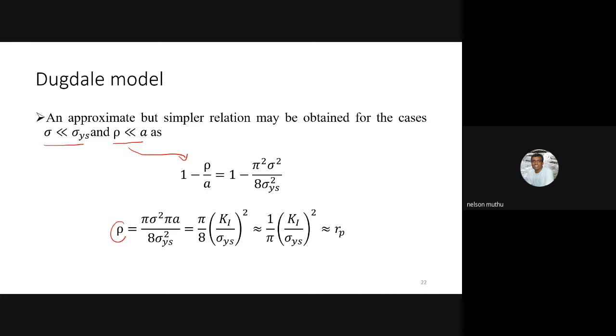Finally, you realize the length of the strip in the case of Dugdale model is equal to pi by 8 (K1 by sigma ys) whole square. It is almost equal to RP. So this is nothing but RP in the case of plane stress, second order estimate. Pi by 8 is approximately equal to 1 by pi. So finally, what we are able to show in the case of plane stress is that both the Dugdale model and Irwin's methodology are able to give you similar results.